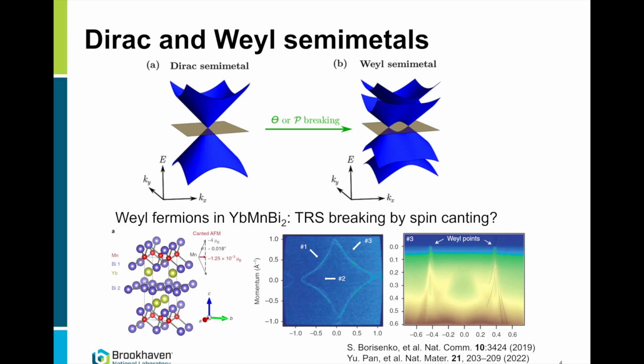And then there was the Zaliznyak et al. paper, and then there was a follow-up paper published in Nature Materials, by the way, where a group measured some bulk magnetization and claimed, yes, there is indeed canting. Now, canting, they claimed in the Nature Materials paper, 0.018 degrees. We were talking moire, we were talking point 0.02 of a degree. Can you imagine a bulk crystal with something that's defined to 0.018 degree? And then, of course, in order to have an effect on an electronic structure, can you believe that 0.018 degree canting of magnetic moment, even of manganese at 4 Bohr magneton, can lead to some serious changes in the electronic structure?